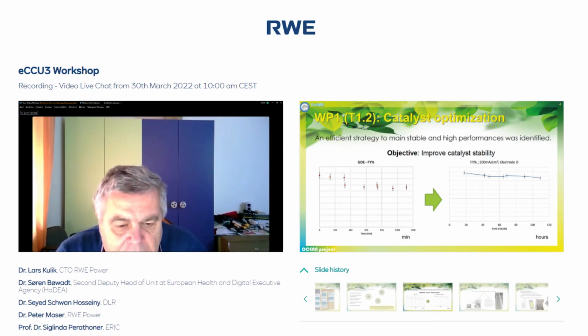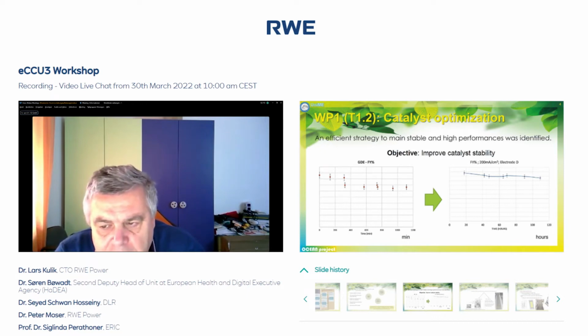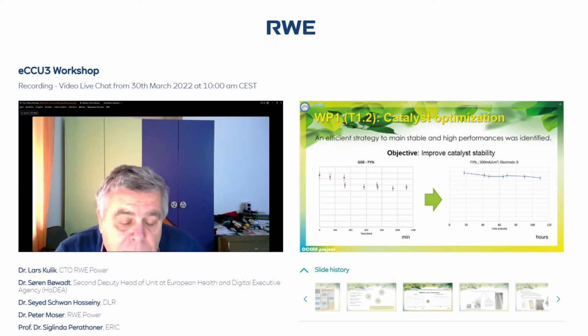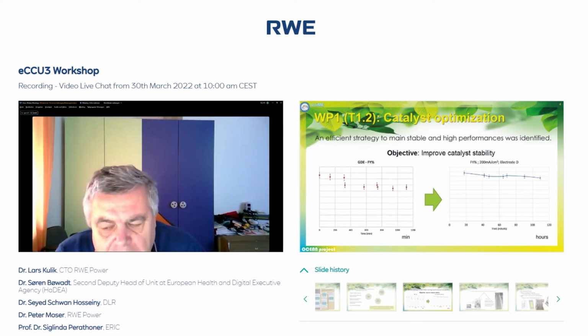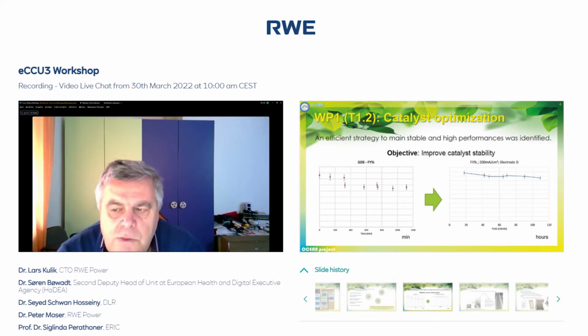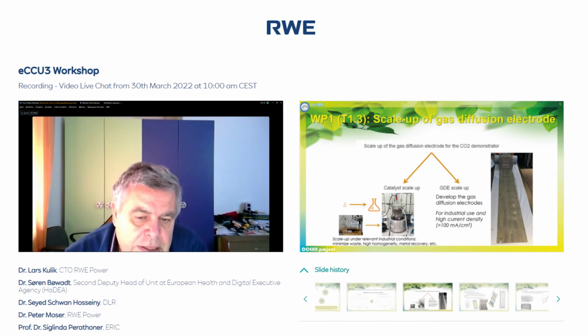Next slide, number 4. Here you see, for example, initially we had a stability of the order of 2-3 hours. And then we improved the performance, especially in terms of design of the cell, and it was possible to obtain stability over 100 hours and even more. I apologize that, due to confidentiality issues, I have avoided putting the numbers in terms of the performance, but let me say that these are relatively high performances, which are quite good also for industrialization of the system.